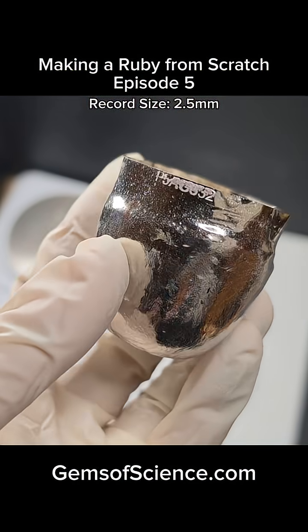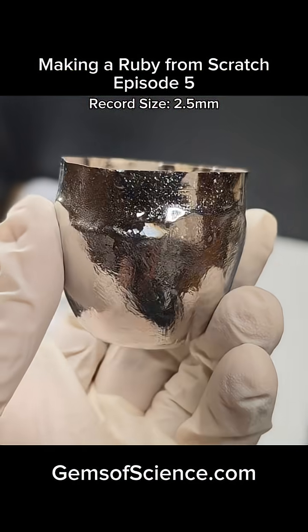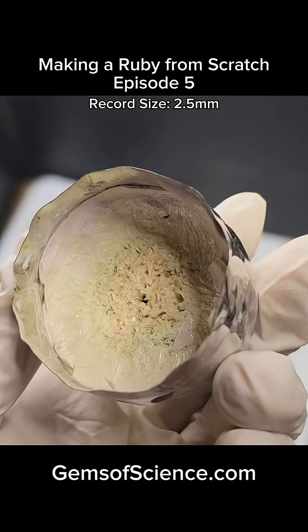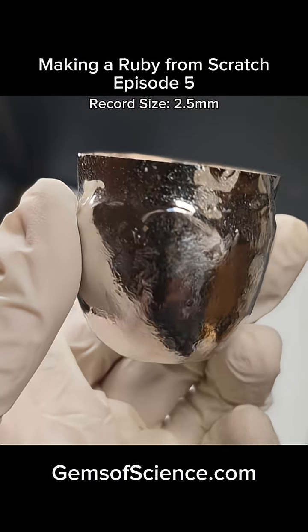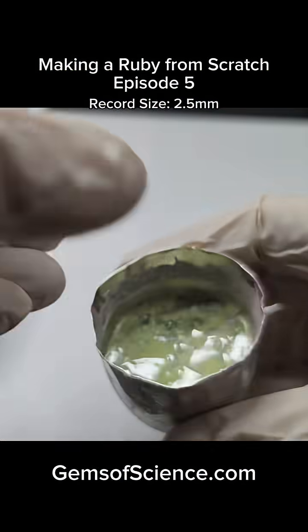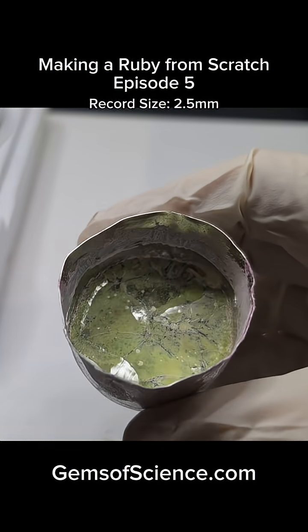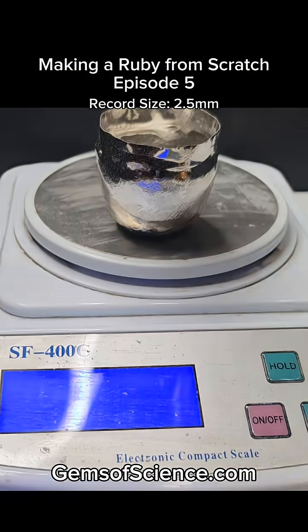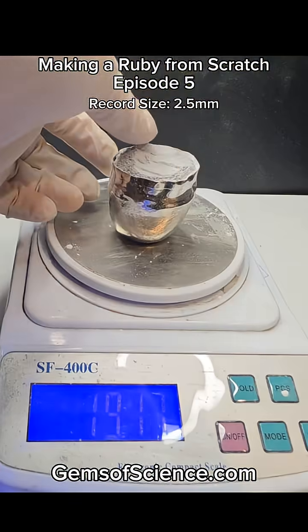And after another 4 days, oh, this wasn't that big before, was it? Yeah, it seems like the lithium carbonate mix expanded a bunch as it cooled and bulged out the walls of the crucible. Fortunately, it didn't break, but that could have been really bad for me. Whew. The tungsten mix still looks cool, but neither of them ended up having any rubies in them. So I decided to retry both of them just with a lot less of the additives mixed in.